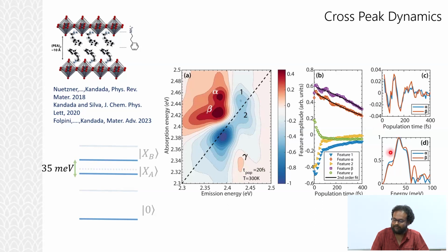and Fourier transform it, you get a beautiful peak around 35 meV, which is the energy separation between these two states. So I have two states exactly like before. I'm creating, along the off-diagonal feature, coherence between these two features. And then you'll see an oscillation at that frequency. It dephases extremely fast because of the very strong dephasing in these materials, but you see it.